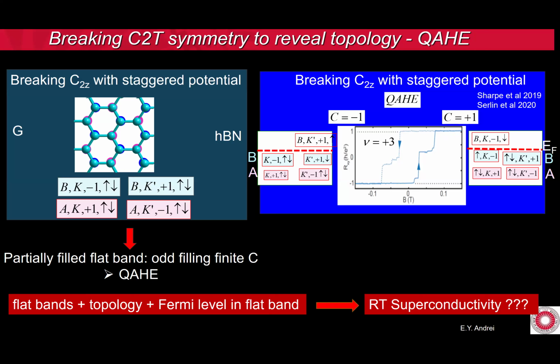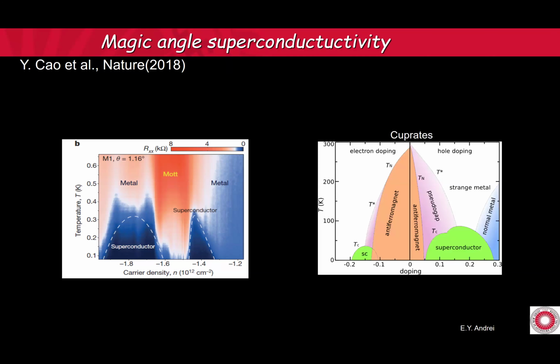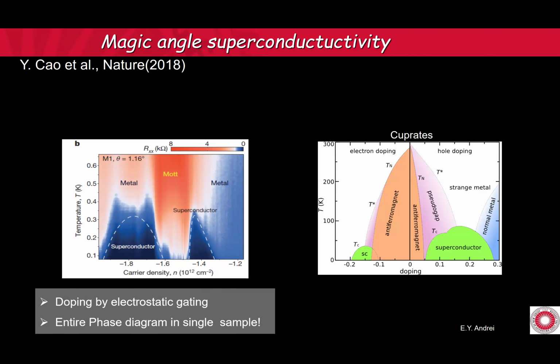Okay, so now the flat band topology, room temperature superconductivity. Where is it? Okay, so indeed, superconductivity was discovered, and this is the famous phase diagram where you see two beautiful superconducting domes that flank an insulating phase, and this is reminiscent of the high temperature superconductors. People got very excited about it. So there's very strong coupling. Tc over TF is 0.2 or so. And the more exciting thing is that instead of having to make a different sample for every point of this phase diagram, all you need to do here is change the doping. You just turn your voltage, and you can plot the entire phase diagram in a single sample.